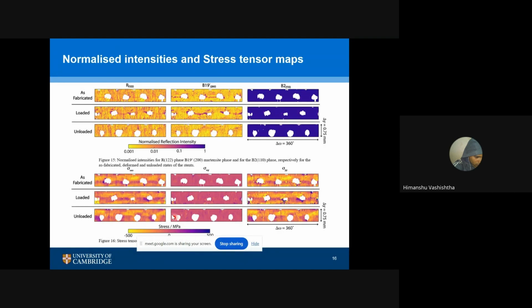One thing I'd like to highlight, for the omega-omega and yy tensor: in this yy tensor or omega-omega tensor, you can see close to these edges, from one edge to another, the high stress regions were there. All the high stress regions were approaching from one corner of the stent gap or stent hole to another. This may be most probably because the stress concentration is higher at this edge, so most of the dislocations or defects are settling in these areas.